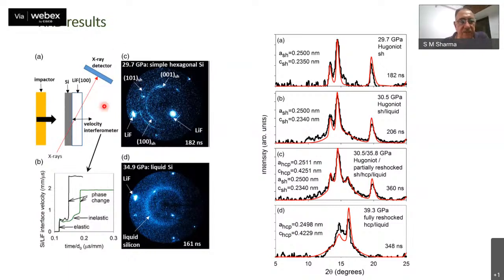These are the X-ray diffraction images which are recorded. This one is, for example, close to 30 GPa. The sharp dots are incidentally from the lithium fluoride single crystal. And you can see the partial rings are representative of a textured phase of silicon and can be identified as 001 of primitive hexagonal or simple hexagonal. This is 101 of simple hexagonal.